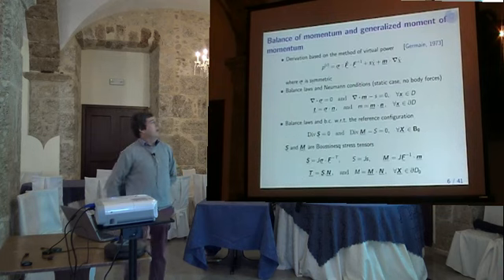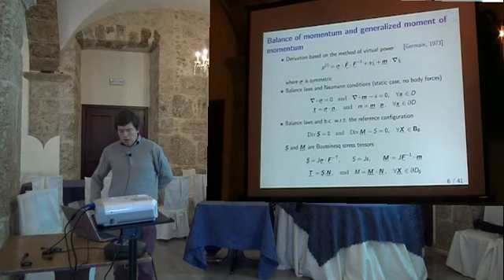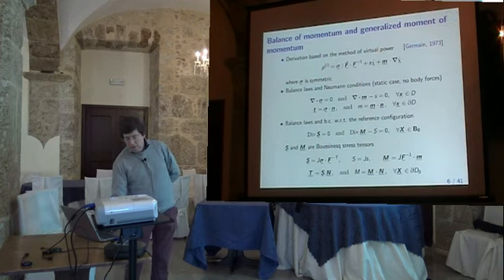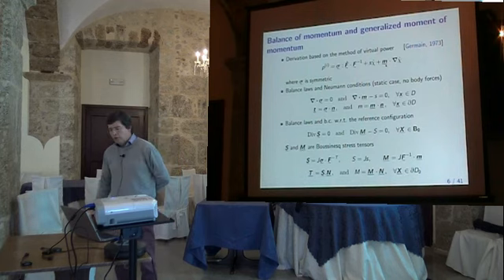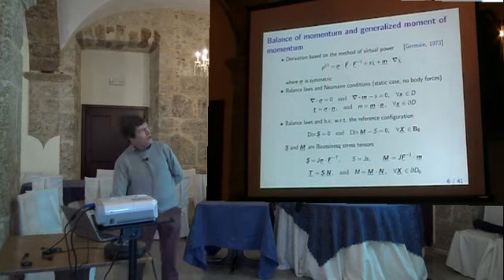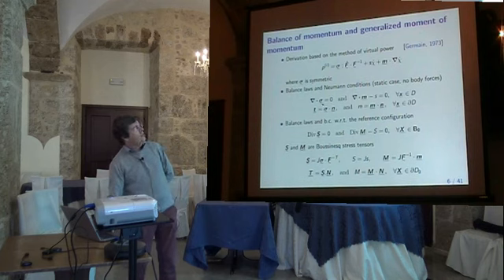So we have a balance equation for that, because due to the gradient, like for the displacement here, you have the effect of the stress. So we have also the effect of the gradient of the micromorphic deformation here, and we have a conjugate higher order stress, which we could call sort of couple stress, in fact. We have balance equations, standard ones, with the Cauchy stress here, the divergence, and the divergence also of the higher order stress here, with the coupling term here, which is conjugate to the evolution of the micro deformation here.